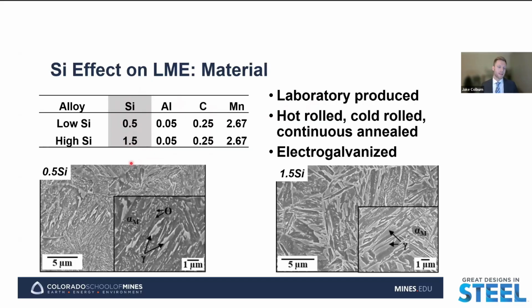If we take a look at the microstructures that we have for these two alloys, we see what we would expect again for a quench and partition microstructure, with relatively high fractions of martensite and some retained austenite present, but also notably this higher fraction of cementite or carbides in the lower silicon containing steel, due to having that lower alloying presence of a carbide suppressor in this alloy.